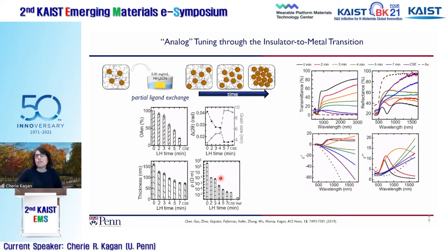The reason we were interested in this was actually not so much the resistivity, but again, their optical properties. If I just focus, for example, on the real and imaginary parts of the dielectric function, you can see here that as you control the degree of the exchange, you start off with something that's an insulator. It starts to dip negative, more negative, more negative. But you can really dial in all the way from an insulator to a metal the optical characteristics of these materials.